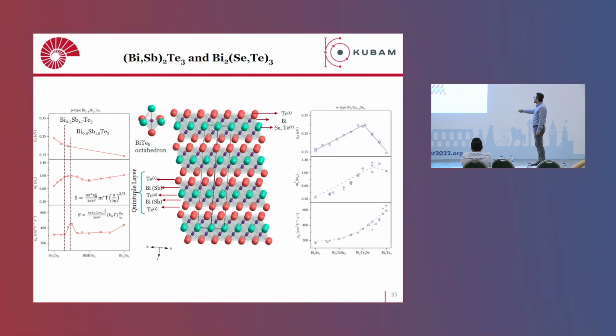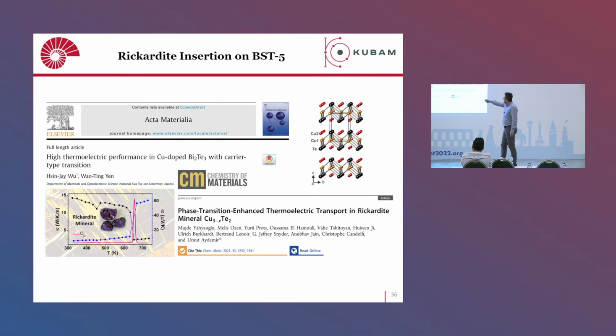For the selenium case, you can do the same. You can basically do a solid solution of bismuth telluride with bismuth selenide. They have the same crystal structure, which means you can combine them in any ratio you want, and you can also optimize their transport properties. So now we saw that in literature, copper is a very good dopant to optimize the thermoelectric properties of bismuth telluride.